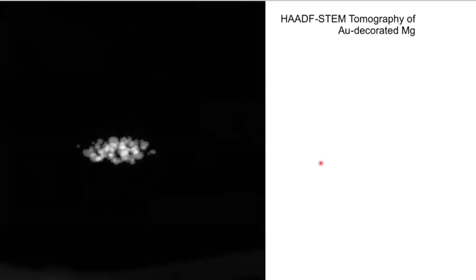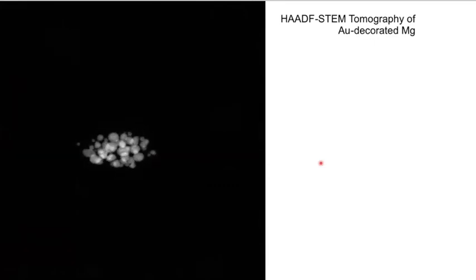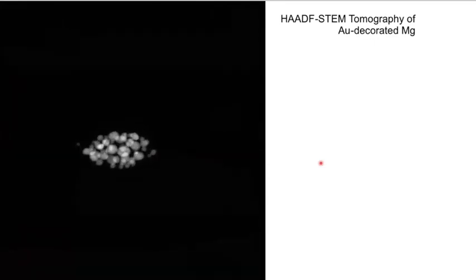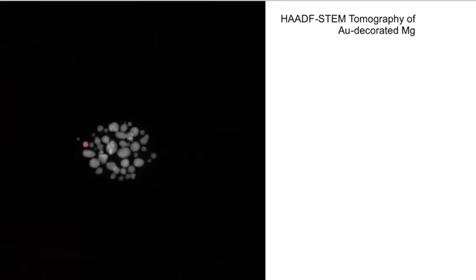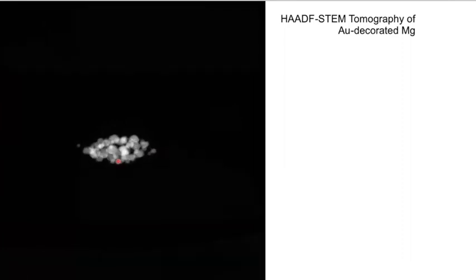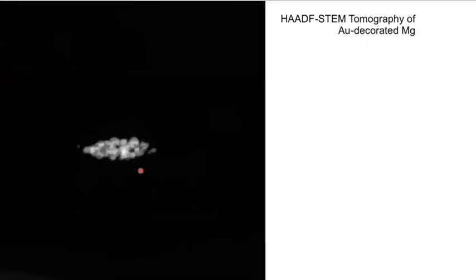And this is to show how difficult it is to characterize these particles because there is a nanoplate of magnesium in here, but there's also the small particles of gold. And the reason why you don't see the magnesium is because of the contrast difference in high angle annular dark field, where you have a Z to the 1.7 scattering probability, and the gold scatters so much more than the magnesium that essentially the magnesium is completely shadowed by this gold. So it makes some characterization really quite tricky sometimes.